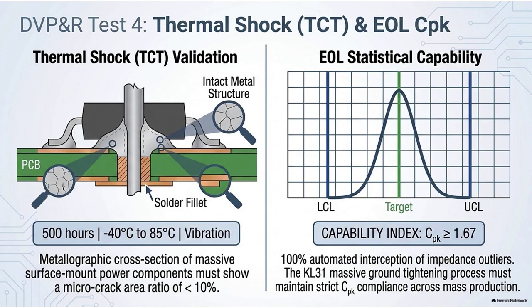Then, a mechanical elevator violently transfers the board into a roasting chamber at 85 degrees Celsius. That's 185 degrees Fahrenheit. And the transition is brutal. The specification demands a temperature rate of change of greater than 10 degrees Celsius per minute. You are subjecting the materials to massive, rapid thermal expansion and contraction. They run this continuous freeze-thaw cycle unceasingly for 500 hours. Often stacked simultaneously with multi-axis electrodynamic shaker tables, introducing random high-G highway vibrations.